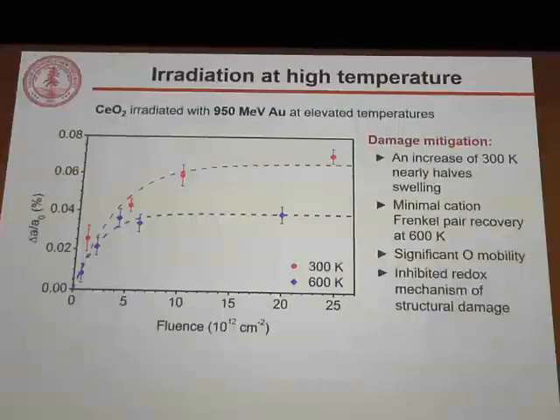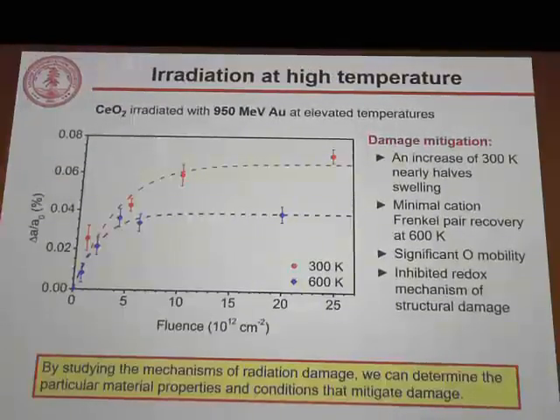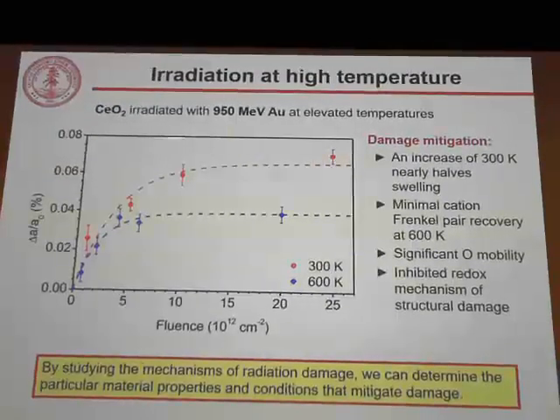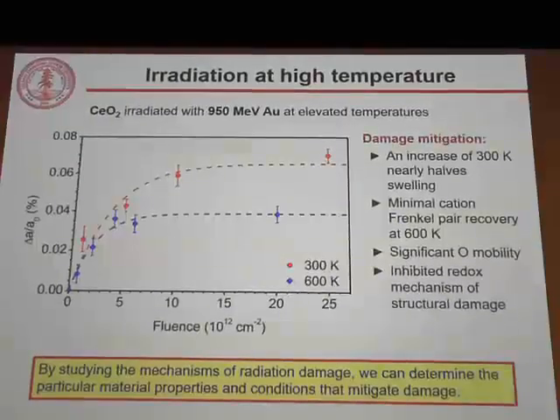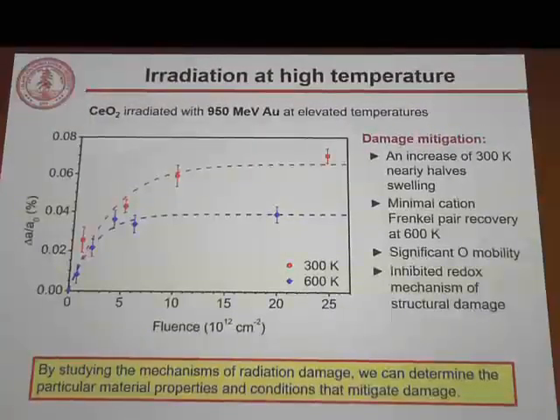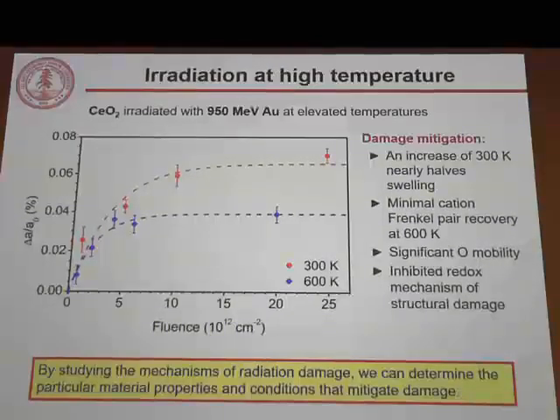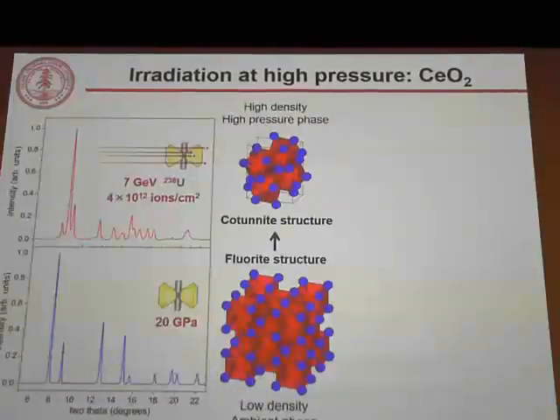And we know that at this relatively low temperature, 600 Kelvin, there's relatively minimal cation Frenkel pair recovery. So it really has to be this oxygen mobility that we're inducing by depositing thermal energy to the material that mitigates this redox mechanism of structural damage accumulation. So what this shows is that by studying these atomic scale mechanisms of radiation damage, we can determine specific material properties or the composition and how that will mitigate damage, and determine conditions such as certain temperatures that might mitigate damage as well. The next thing we can look at is combining irradiation with high pressure.